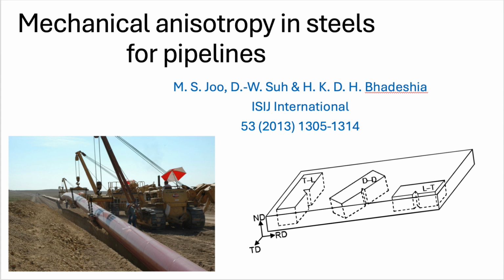How? Because the crack, instead of running straight through, gets diverted along these weak banded layers. Each time it splits or delaminates, the separation itself absorbs some fracture energy. It forces the crack to take a more tortuous path. So it kind of interrupts the main crack propagation, absorbs extra energy, making those side cracks. Exactly. It's called delamination toughening. So, the same feature that hurts toughness in the ductile regime can, paradoxically, provide a boost in the brittle regime.